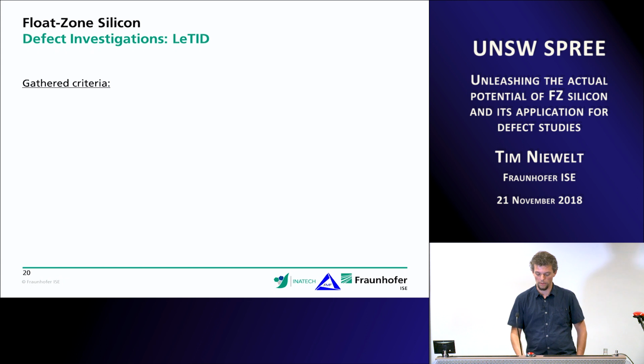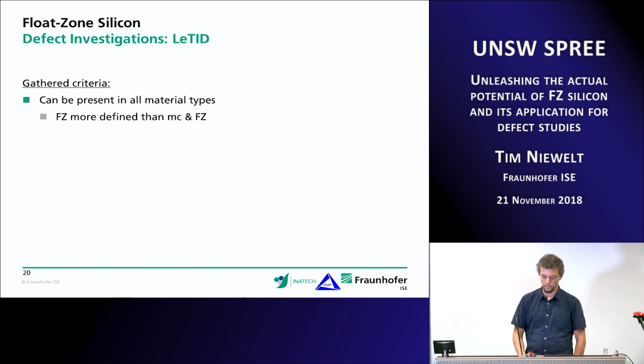Okay, let's collect some of the insights that we've seen. So yes, the degradation can be present in all material types, further indicating that it's actually a bulk defect and not something related to surface degradation. And the great thing about float zone silicon, I should have mentioned that earlier, is that it is a very defined material. There's not too much dirt in it, especially when you compare it to multicrystalline silicon, where you have structural defects and a lot of contaminations, and you just don't know what's happening there and what's moving around or not moving around. In float zone silicon, there's not a lot of stuff to begin with, so it's way easier to find candidates for the defect, or candidates that play a role in the defect.